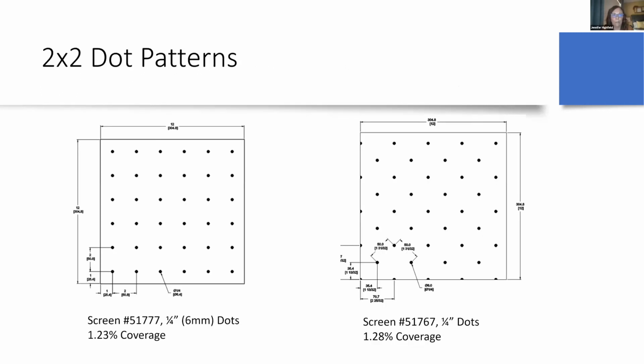Here are 2 of the more minimal dot pattern options. These are 1/4 inch dot sizes with just over 1% coverage that follow the 2x2 spacing rule. We're really seeing that architects are preferring these more minimal coverage patterns to meet the bird-friendly codes. Here are 2 examples of common bird-friendly 1/8 inch thick line patterns with 4-inch vertical spacing or 2-inch horizontal spacing, and range from 3% to 6% coverage and are within the 2x4 rule.